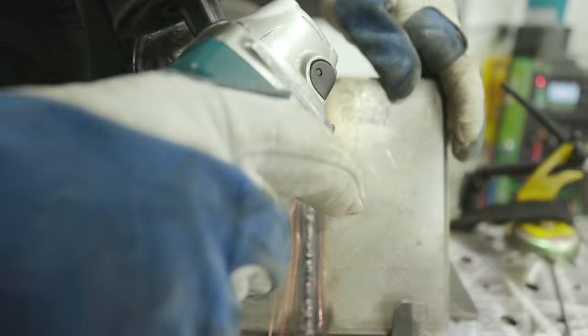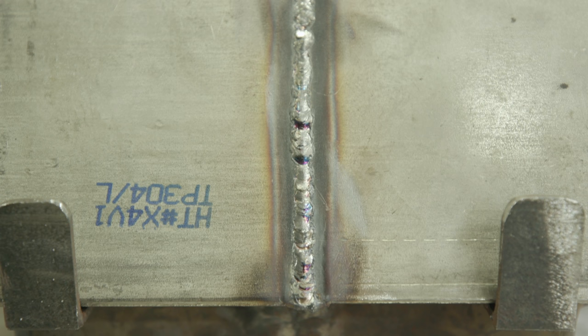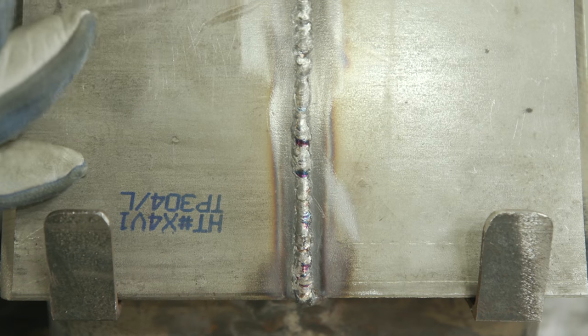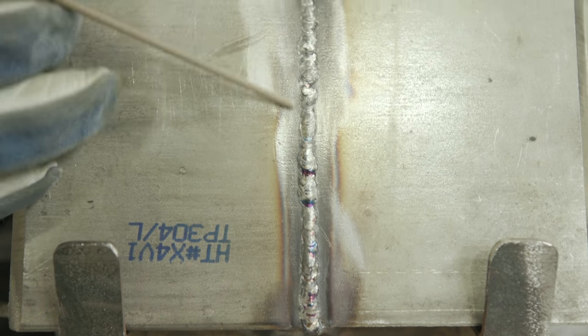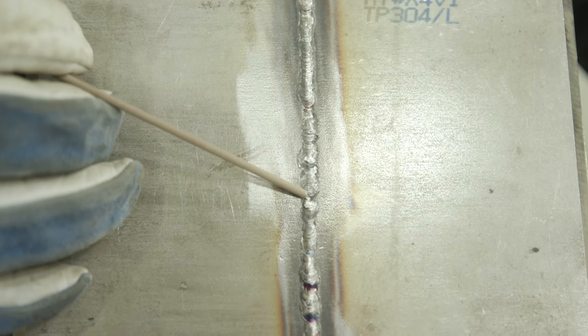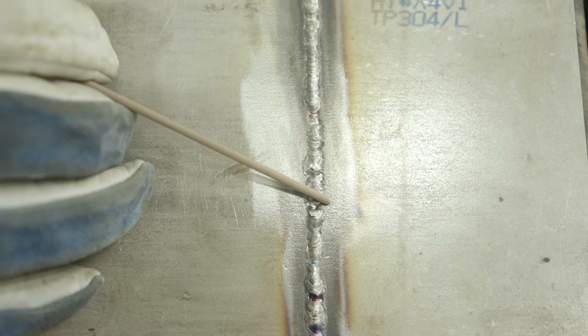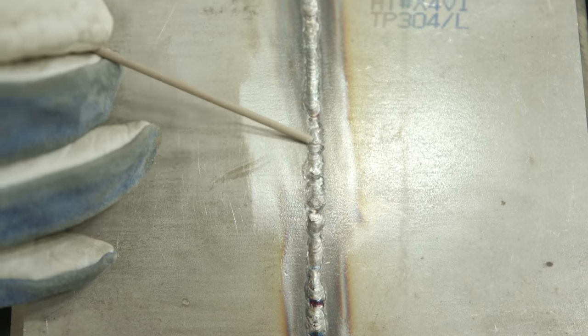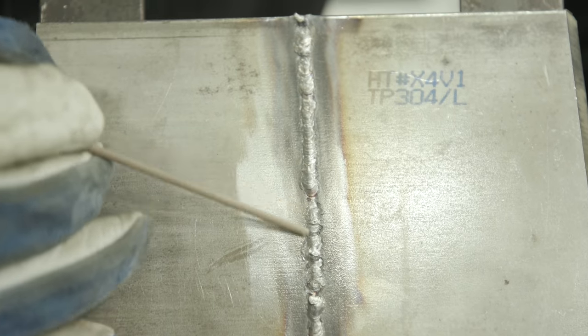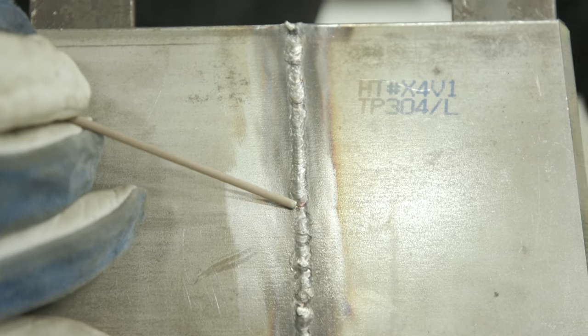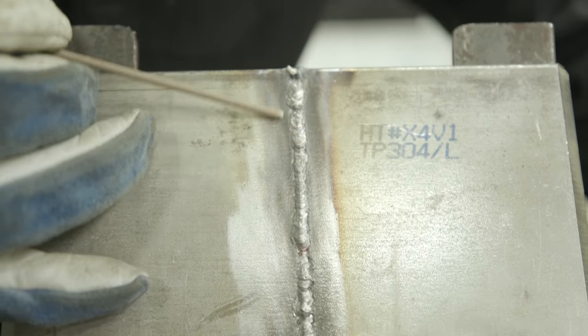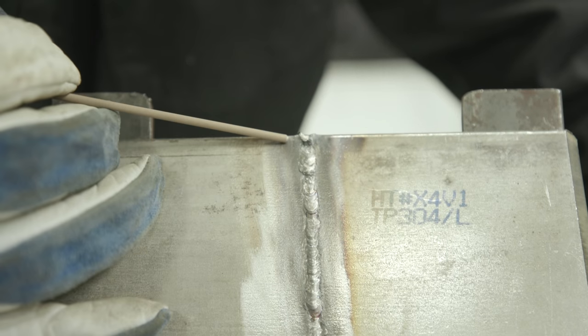Since we got this slag cleaned off, we're going to flip this plate around and check the root out. Starting down here at the bottom - nice penetration, both walls, both bevels. The plates broke down. A little flux right here, it's not no undercut, just needs to be cleaned off more. See my restart right here? I could have sat a little bit longer and fed it in there, but still there's no inclusion, nothing.